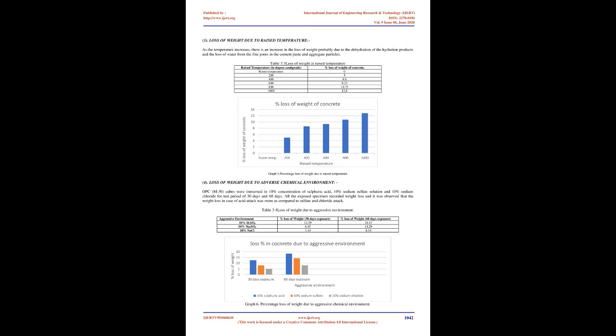2. Compressive strength against adverse chemical environment. 3 specimens in each acid, sulfate, and chloride solution were tested for compressive strength after the curing time, and the unit weight of specimens was noted before the test. 4. Loss of weight due to adverse chemical environment. OPC M30 cubes were immersed in 10% concentration of sulfuric acid, 10% sodium sulfate solution and 10% sodium chloride for test periods of 30 days and 60 days. All the exposed specimens recorded weight loss, and it was observed that the weight loss in case of acid attack was more as compared to sulfate and chloride attack. Graph 6. Percentage loss of weight due to aggressive chemical environment.